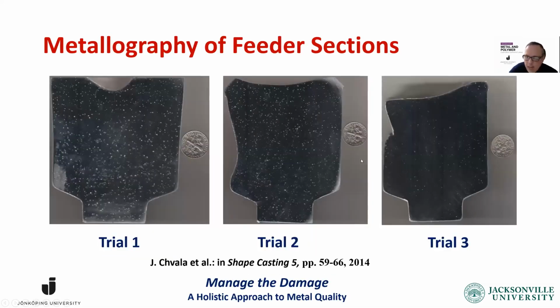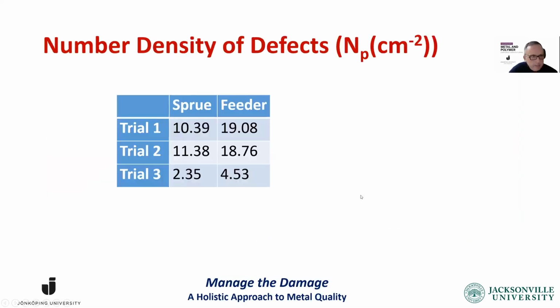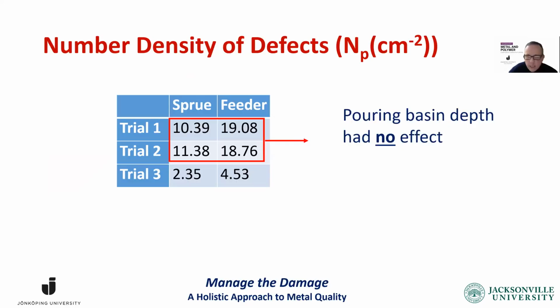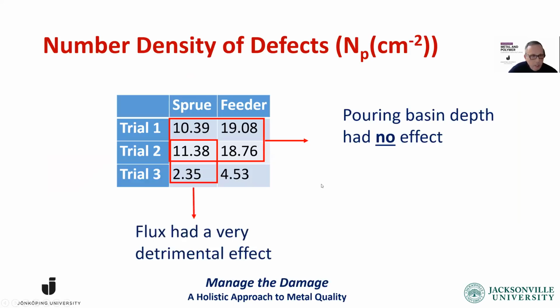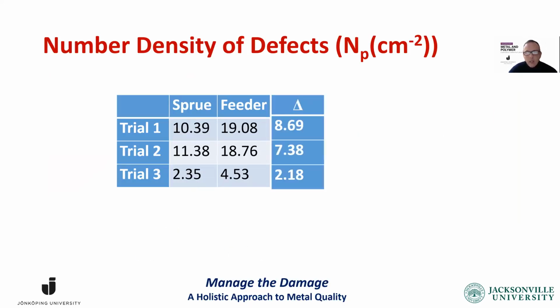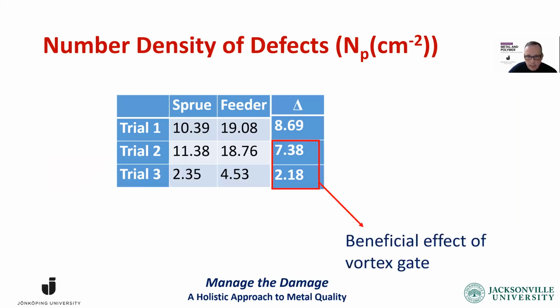These are the risers, feeders that we have sliced in the middle. We take a look, but it's the same story. So we could look at the sprue feeder. When we look at this, the pouring basin depth had no effect. That gave us good information. When we look at this, flux had a very detrimental effect on the quality of the casting. And overall, you can see the beneficial effect of the vortex gate. So there's a lot that you can gain by looking at what you already have.